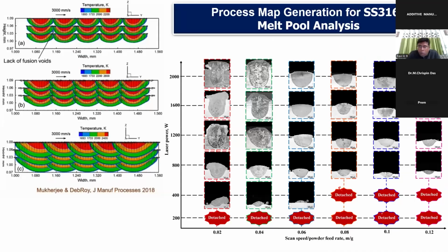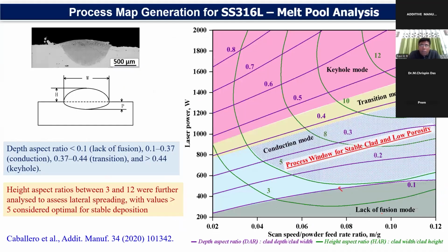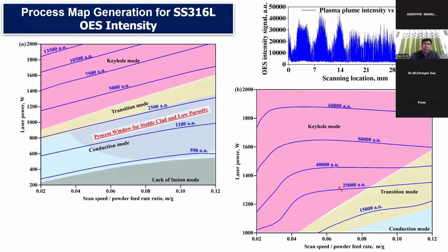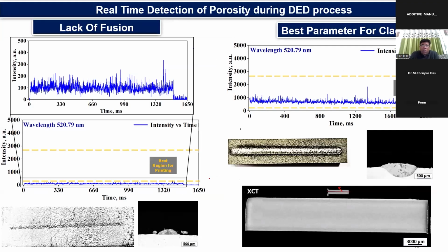I'll not get into too much detail. Using this technique, we were able to identify that for each intensity I get, which I told you is in arbitrary units, by understanding this arbitrary unit one can tell whether you are in the keyhole regime, or in a transition regime, or in the ideal processing window, or in a lack of fusion mode. So we were able to capture it, and we have validated it with experiment.